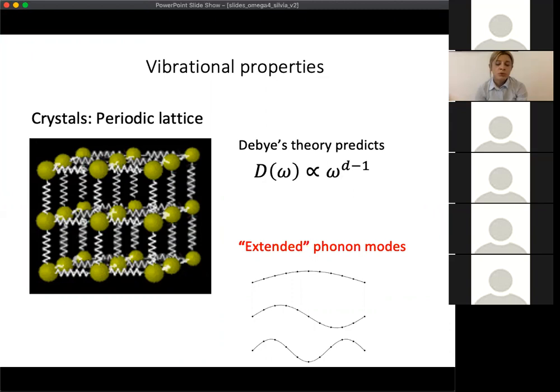This has been also demonstrated by our group in a recent work in PRE 2019, where we can see the first bond breaking of silica glass and we could predict the locus of this failure by looking at the smaller frequency modes. Now let's go to the vibrational properties. From the physics textbook of solid state theory we know that for crystals, which are characterized by a periodic structure, the famous Debye law holds.